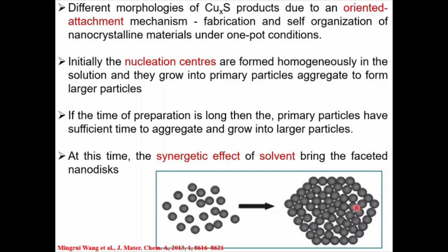You should be closer to the boiling temperature of the surfactant, but not more than the boiling temperature of the surfactant, and the solution added through the other arm should be cold, not hot. At what temperature you initiate the growth is also an important parameter. So the surfactants, time, and temperature, when you identify the proper solvent, decide the evolution of shape and selectivity of the sizes.